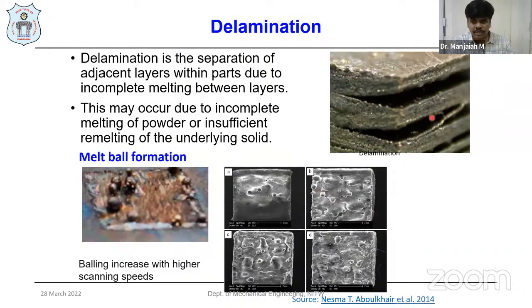You can see layer delamination takes place because of the separation of the adjacent layer from the previously deposited layers, due to incomplete melting of these layers. This may occur due to incomplete melting of the powder or insufficient remelting under solid conditions. These kinds of defects will be there when melt ball formation happens. This melt ball formation is because of the scan speed as well as the laser power.